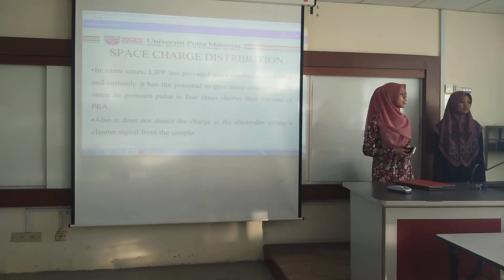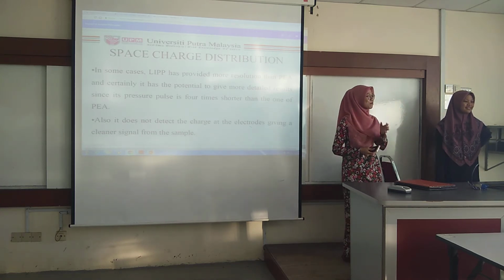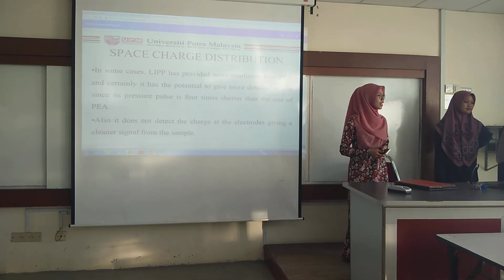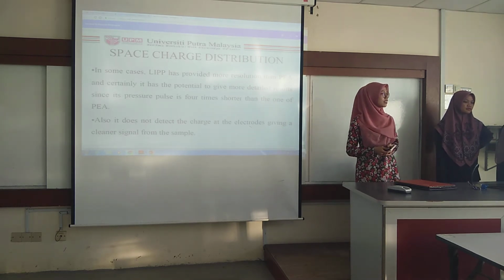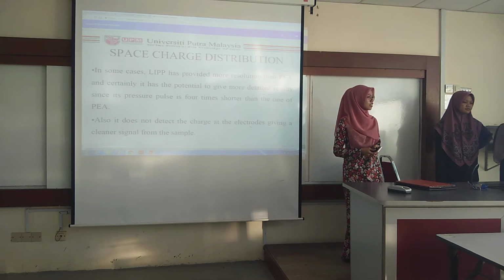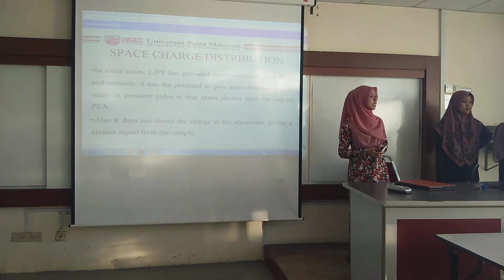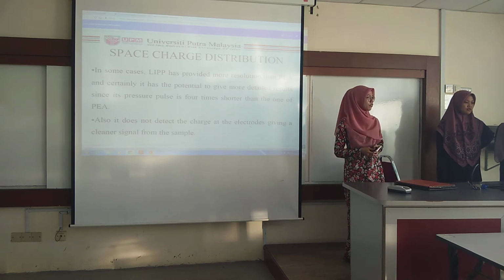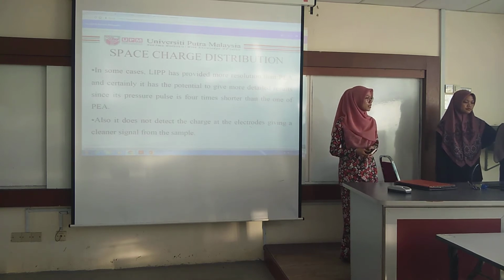In some cases, LIPP has provided more resolution than PEA, and certainly it has the potential to give more detailed results, since its pressure pulse is 4 times shorter than that of PEA. Also, it does not detect the charge at the electrode, giving a cleaner signal from the sample.